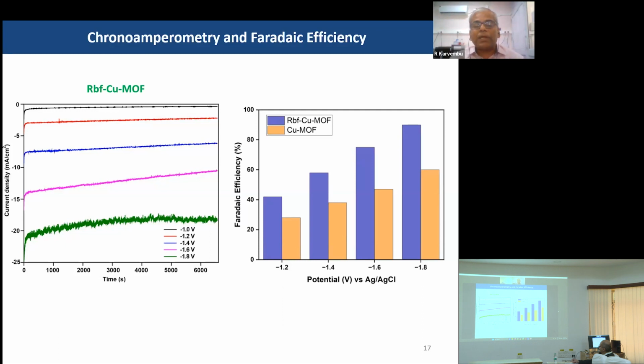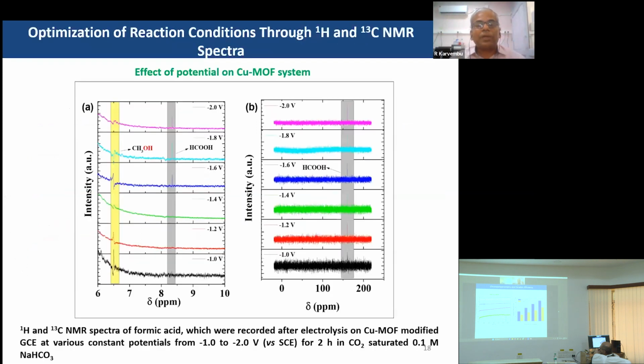We calculated the Faradaic efficiency at different potentials, and at -1.8 volt, the Faradaic efficiency of the system using riboflavin modified copper MOF is 90%, whereas the Faradaic efficiency of the pristine copper MOF is around 60%. So there is significant enhancement in Faradaic efficiency when we use riboflavin modified copper MOF as a catalyst for reduction of carbon dioxide. This gives the selectivity of the reduction process.